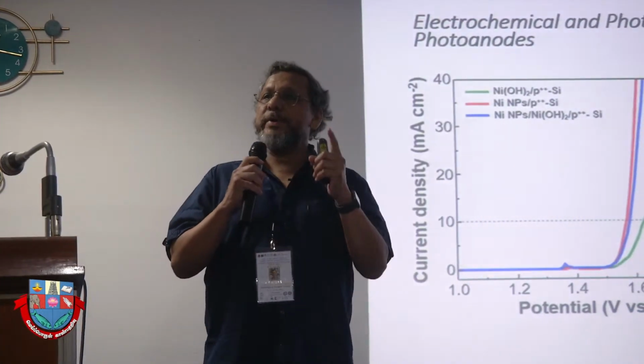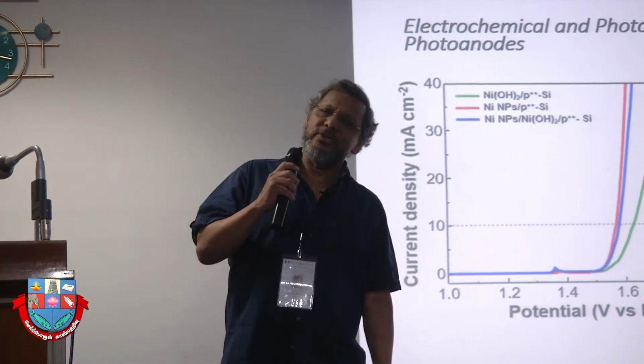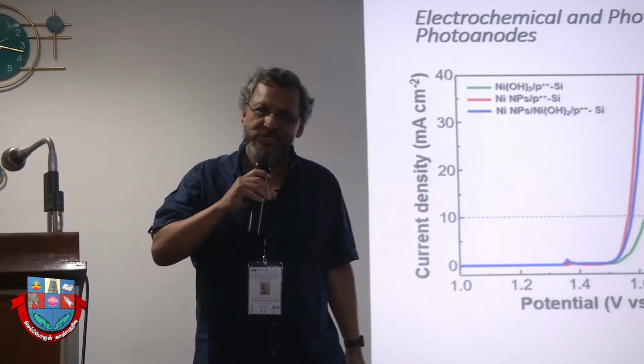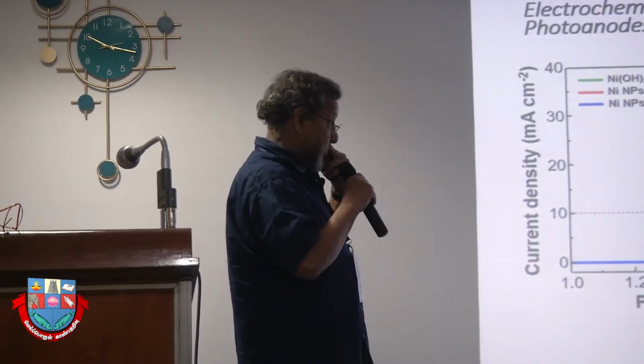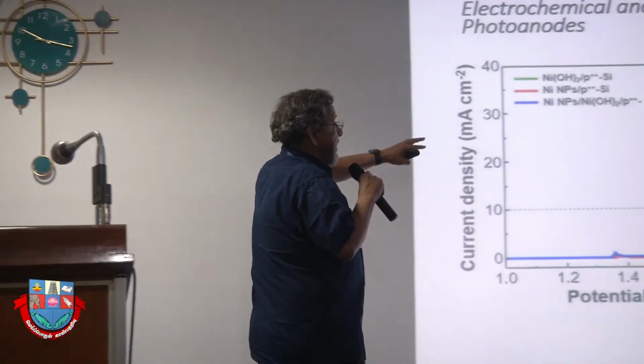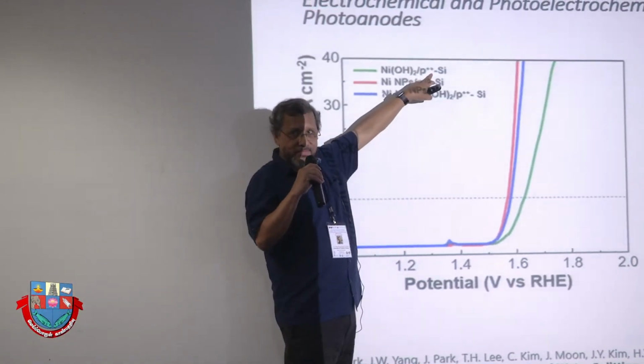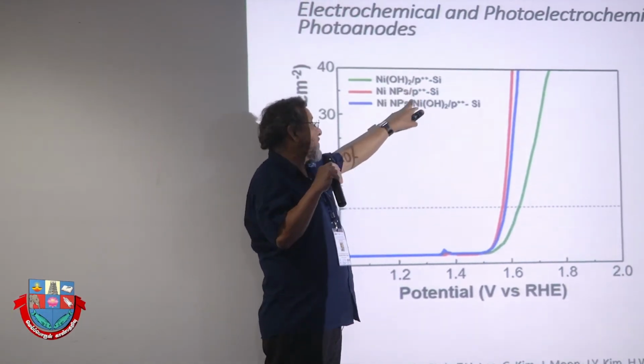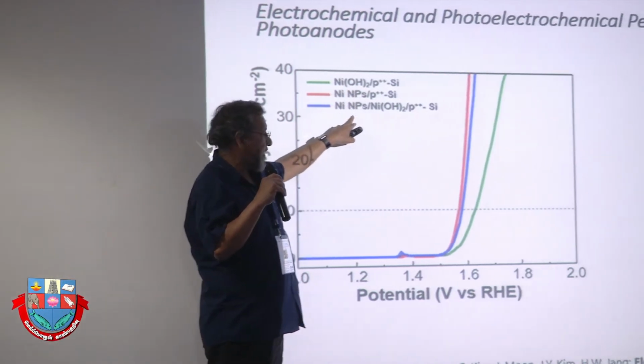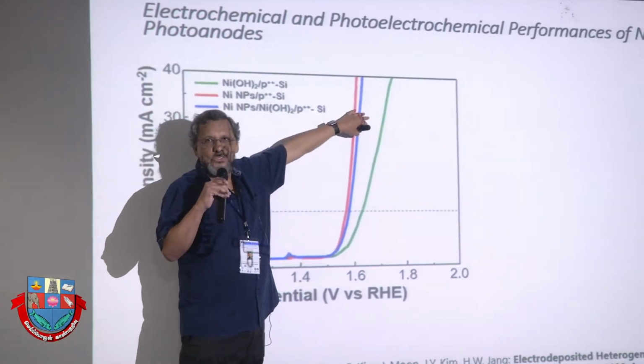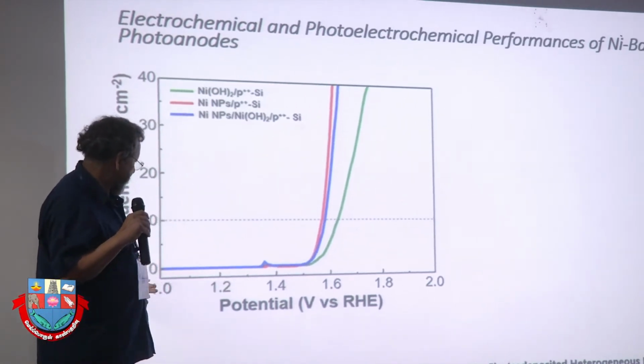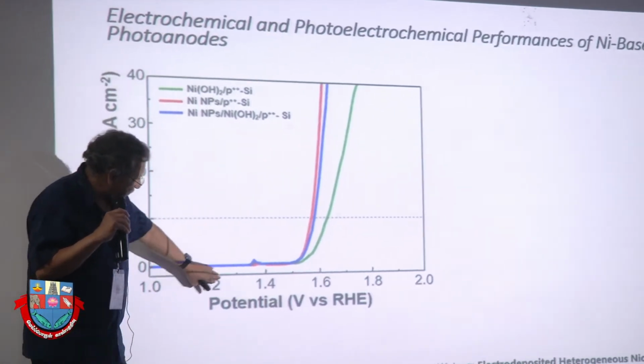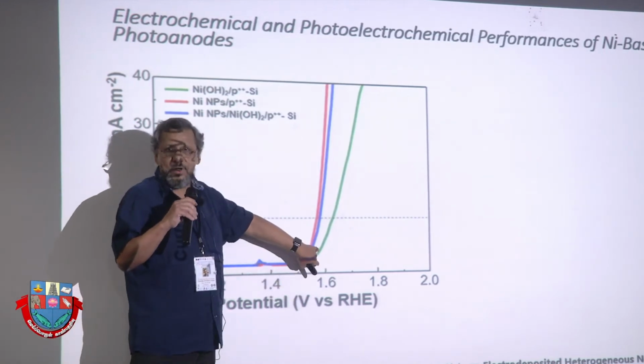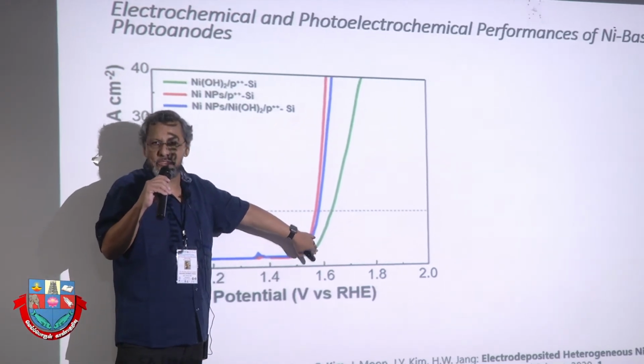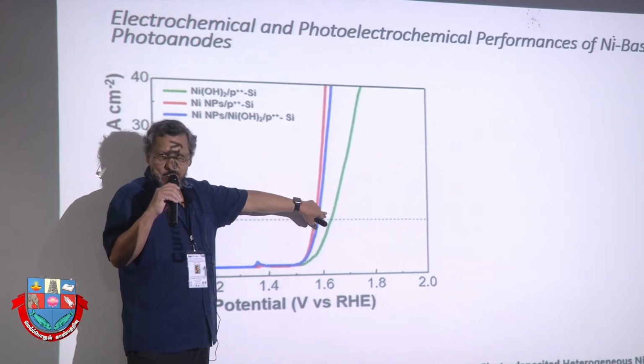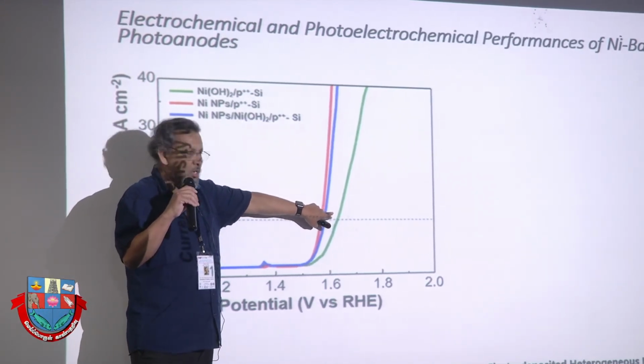I would like just to show a very recent example that was not developed, unfortunately, in my group, but by some other group, a Korean group, for example. And that's interesting, the principle. Look here. They use highly doped silicon, like a metal in that case, and they deposited this species here, and they evolve oxygen. Look at the potential. The thermodynamic potential is 1.23, and that goes around 1.6 volts. Similar to the best catalytic material like iridium oxide.